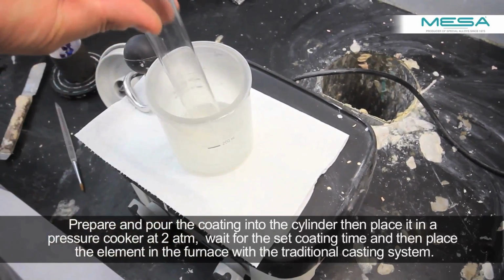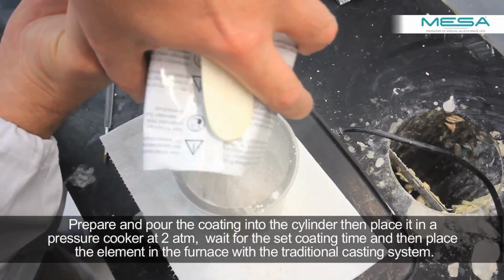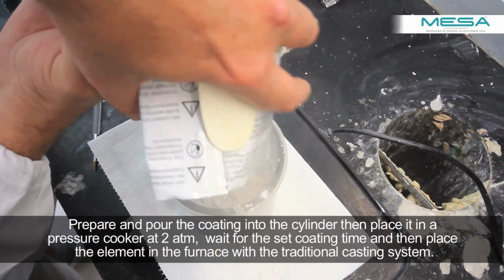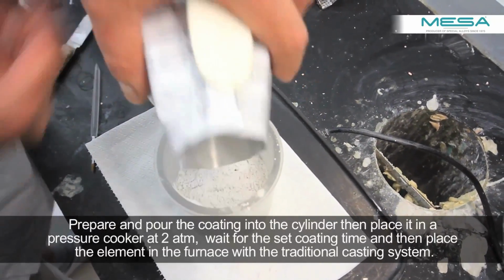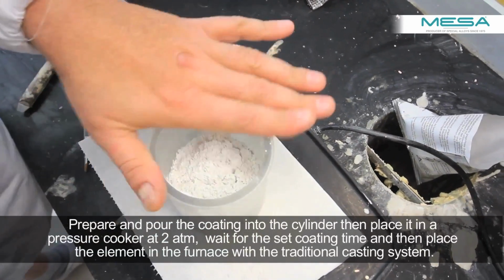Prepare and pour the coating into the cylinder, then place it in a pressure cooker at 2 atmospheres. Wait for the set coating time and then place the element in the furnace with the traditional casting system.